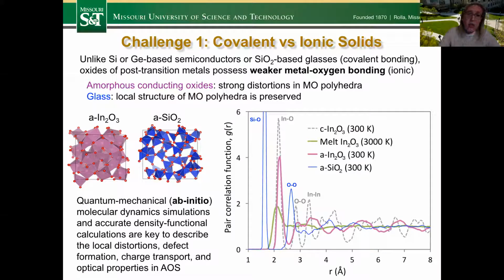So because of this weaker metal-oxygen bonding and strong distortions, but also because we are interested in the transport properties of this material, defects are very important, and optical properties again are very important. We have to use ab initio molecular dynamics and density functional or hybrid functional, actually go beyond the DFT a little bit, to describe these local distortions, defect formation, carrier transport, carrier generation, and optical properties in these materials.